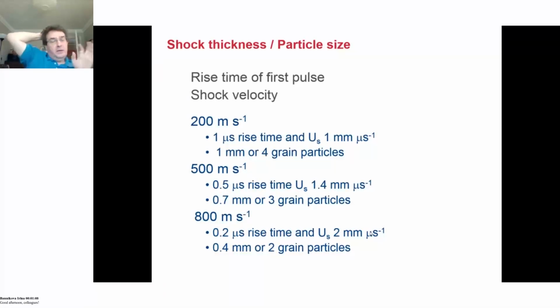At 500, you're now down to 0.7 of a millimeter, or 3 grain particles approximately. And then when you go to 800 meters a second, you've got 2 grain particles between being undisturbed and being fully compacted. This shows that there's effectively a doubling of the compaction in the system. So you've got this far more violent process occurring.